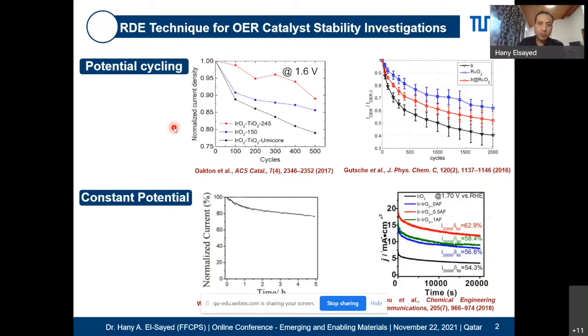So for those of you who already know, one of the best catalysts for oxygen evolution is iridium. Ruthenium is also very active, but it's not stable. So iridium-based catalysts are very active towards the oxygen evolution reaction. And what you can see from this slide is that people not only try to use the RDE to determine the activity of the oxygen evolution reaction, but they also use it to study the stability of the OER catalyst.